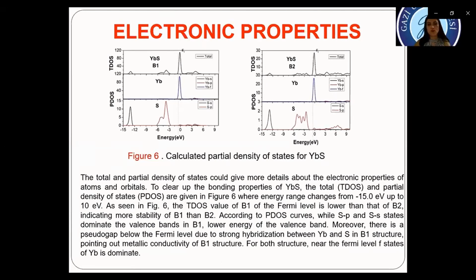According to the partial DOS curves, S-s and S-p states dominate the valence bands in B1 at lower energy. Moreover, there is a pseudogap below the Fermi level due to strong hybridization between ytterbium and sulfur in the B1 structure, pointing out its metallic conductivity. For both structures near the Fermi level, the f states of ytterbium dominate.